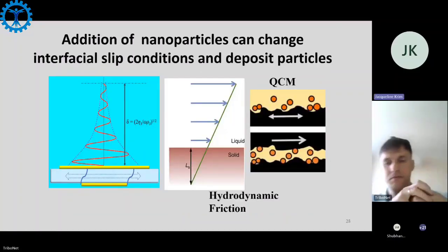So when those particles and when that interface starts slipping, rather than staying stuck at the interface, the QCM is quite sensitive to that. We measure the frequency and the damping forces. So if this were superfluid helium, there's no response at all. It's just perfectly slipping. Otherwise, if it's a no-slip boundary condition, we have a very well-documented exponential decay of the motion of the liquid into the bulk.